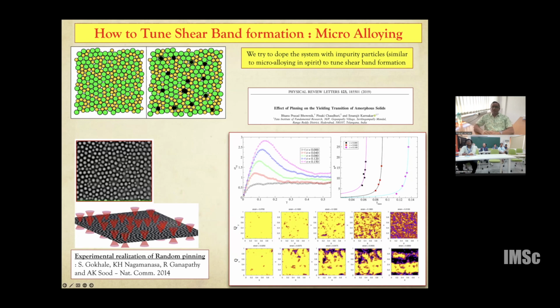So the concept that we used is microalloying. Our crude model of microalloying was to fix a few particles, which we call pin particles, and we do it randomly, which is why this is called the random pinning protocol. Using this method, you choose a set of particles randomly and freeze their position. When you deform them, they can move affinely, but all non-affine motions are suppressed. And we looked at the yielding process in this kind of scenario.